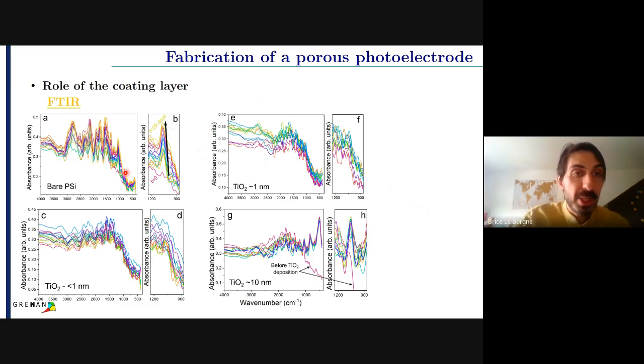So here you have the bare silicon. Of course, we need to compare it with bare silicon, and you have the 29 days here, and we focus here on this wavelength that corresponds to the peak related to Si-O-Si bonds. And you can see there is an increase. So after the first etching, you can see there is no peak. And after 29 days, you have this increase of the peaks. So of course it's oxidizing, and there is a slight shift because the angle of the bonds is moving with the time.